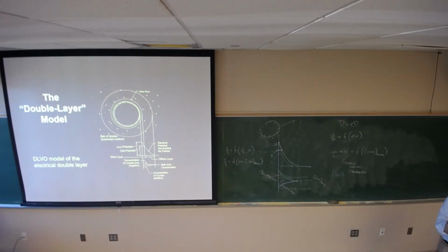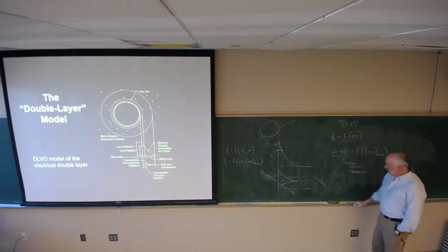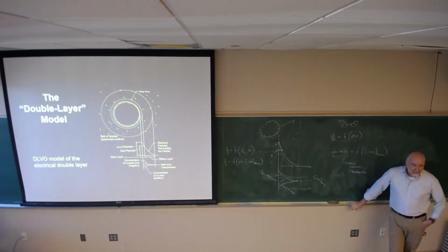That can be complicated in this way. Make up a suspension, okay, and change the pH, and then you measure the zeta potential. But when you change the pH, you are corroding the surface of the particle, right? So now you are creating charge on the particle surface. You are potentially dissolving the surface of the particle. That can change your ionic strength.